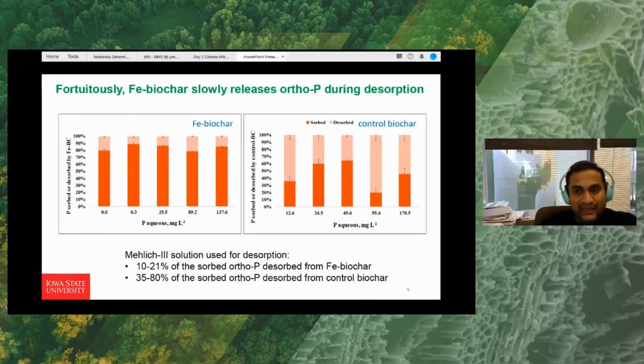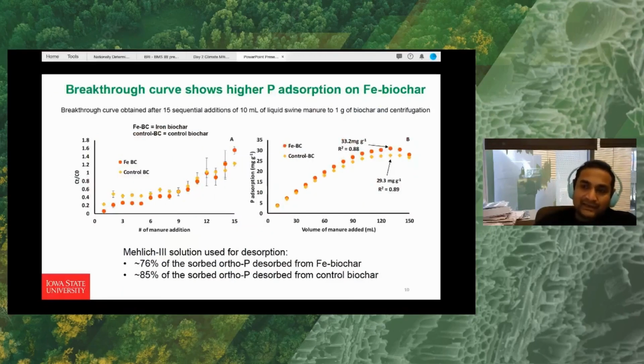So we have used the Mehlich 3 solution for the desorption study. Around 10 to 20% of the sorbed ortho-P desorbed from the iron biochar, and around 35 to 80% of the sorbed ortho-P desorbed from the control biochar. Next slide, please. So we did a column leaching study, and we did the breakthrough curve of the